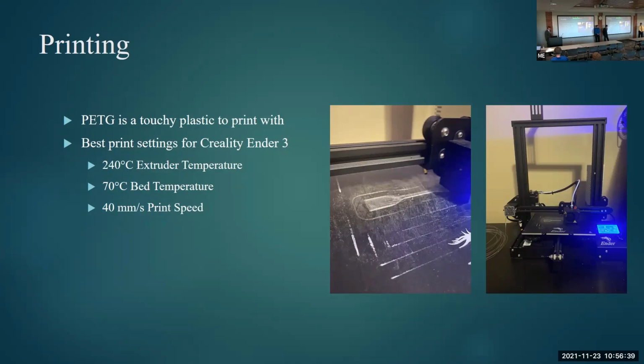Printing with PETG is very common, but it's a little bit touchy to work with as it's going through a printer. There's a very select range of print temperatures that the filament will actually go through smoothly and print evenly. Currently we're printing with a Creality Ender 3 printer, and we found that the extruder temp at 240 degrees C with the bed temp at 70 degrees C and the print speed of 40 millimeters per second helps with the smooth flow of plastic through the printer along with bed adhesion. We do rub a glue stick onto the print bed before the print to help with that bed adhesion. And then that's when that 70 degrees C comes into play. It just helps the material stick better and refrain from warping against the prints.